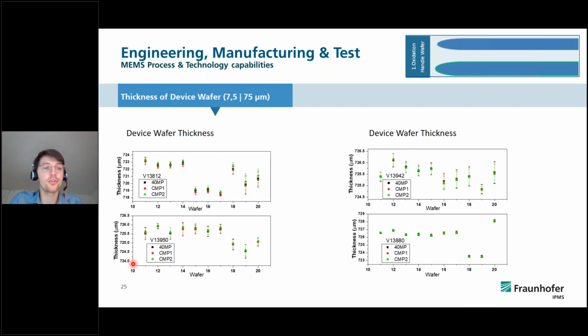What we also measured was the thickness of the device wafer. This is what I basically mean. We started with monitoring wafers, which are typically 720 to 725 microns thick. And here we need to know how thick they are in particular, because we needed to go down to 7.5 microns, and you can only get down to these values if you know the exact numbers of the wafers that you have up front.